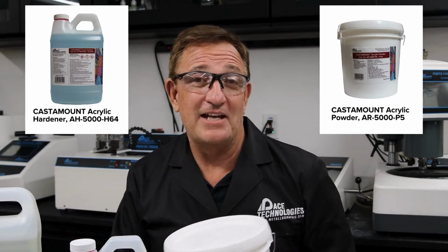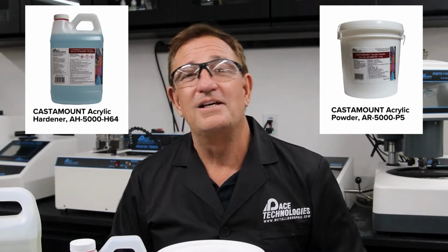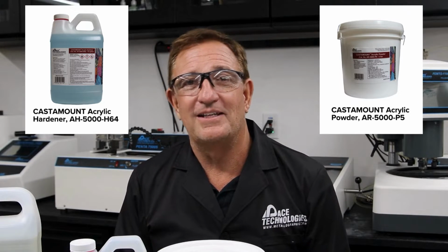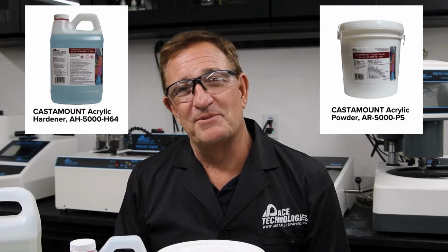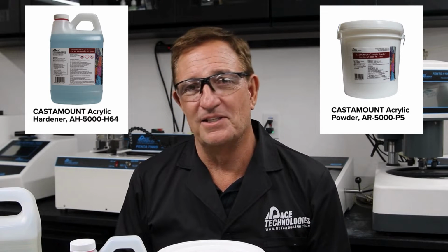The advantage of using an acrylic is that they do cure very quickly. So if you have to turn around samples very quickly, acrylics are usually the best. The disadvantage of acrylics is that it also generates a lot of heat, so you'll get a little bit more shrinkage. So it's a little bit of a trade-off between speed versus the quality of the mount.